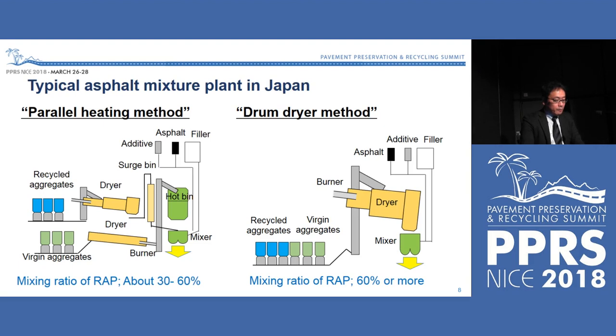Let me mention the outline of the parallel heating method and the drum dryer method. An illustration of the parallel heating method is shown on the left. The parallel heating method is the most commonly used type. Approximately 70% of all is the parallel heating method. This method uses a separate dryer and drum for RAP and virgin aggregates, and uses a separate drum for drying and heating RAP. This method can eliminate the moisture of RAP and heat RAP without thermal degradation.